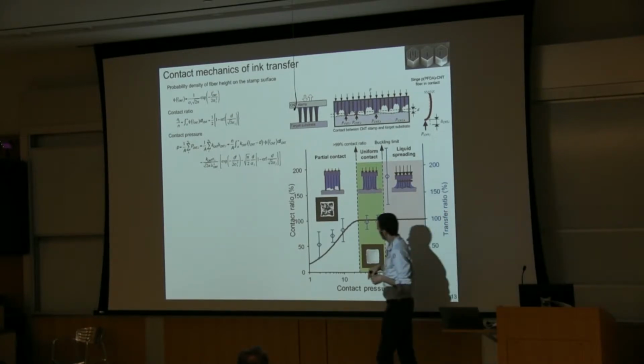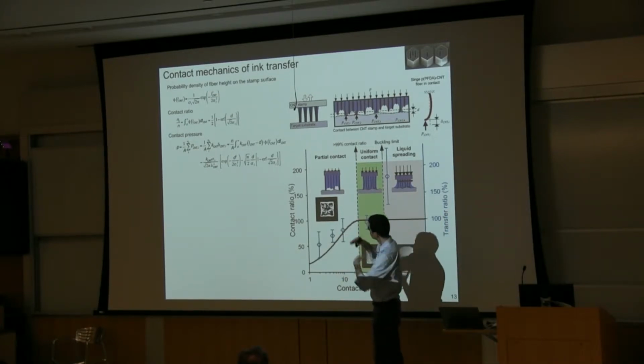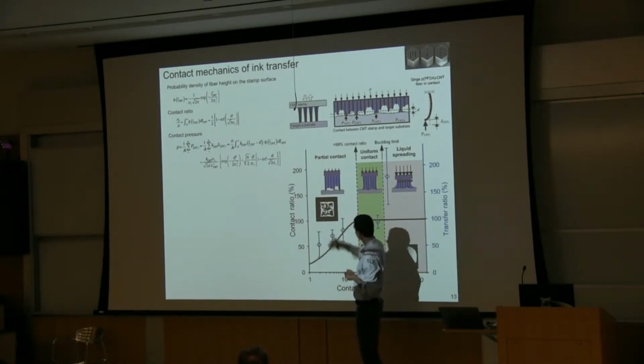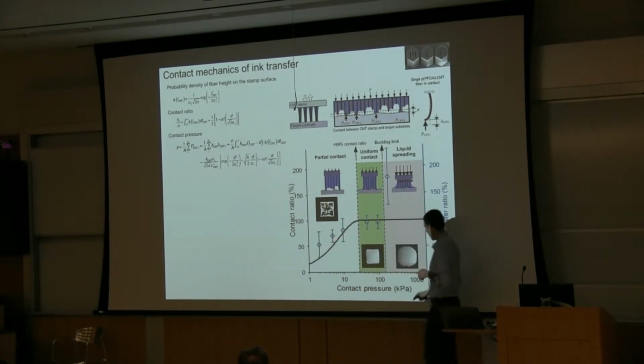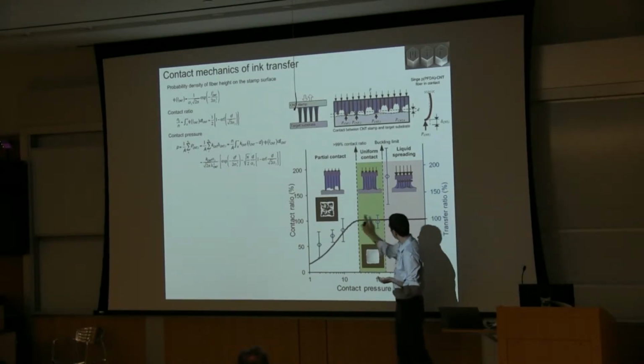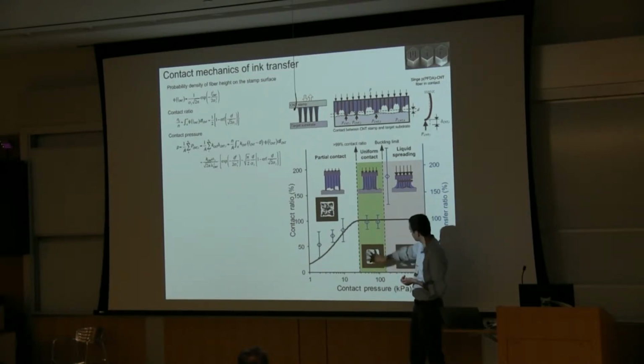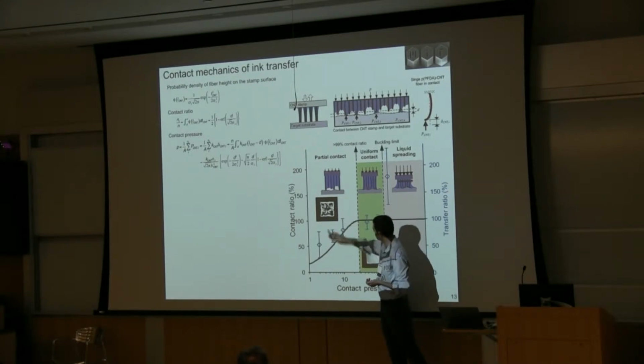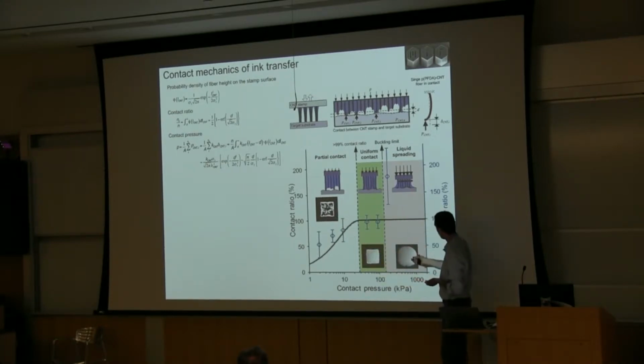This is a plot comparing experiments to this contact mechanics model, where the vertical axis is the contact ratio and the horizontal axis is the contact pressure, and it basically says there's about a tenfold range of pressure where we get good printing, where the printed feature matches the stamp. If pressure is too low, mechanical contact is incomplete, and rather than printing a solid square, you print this kind of random hollow pattern, and if pressure is too high, you overprint.